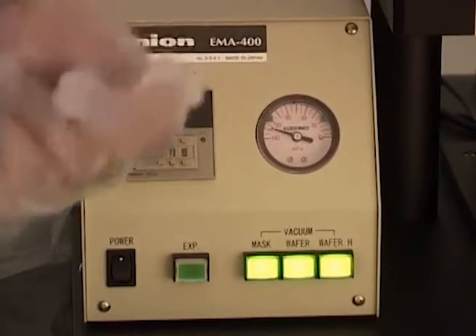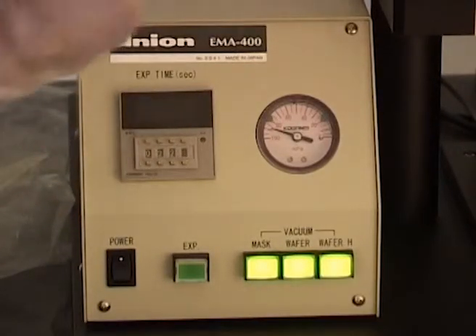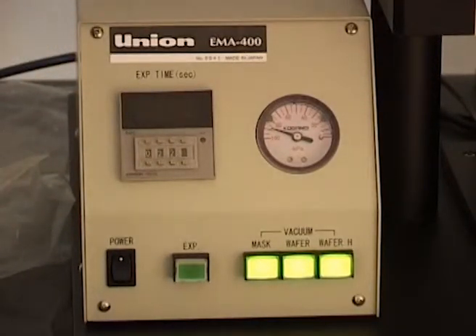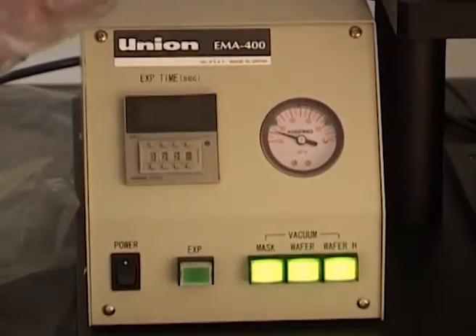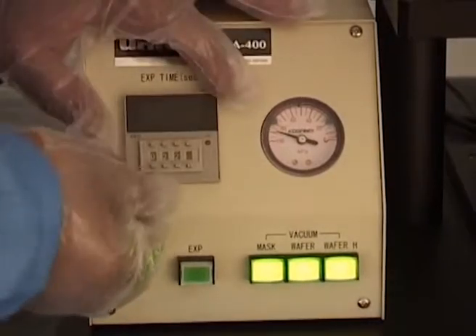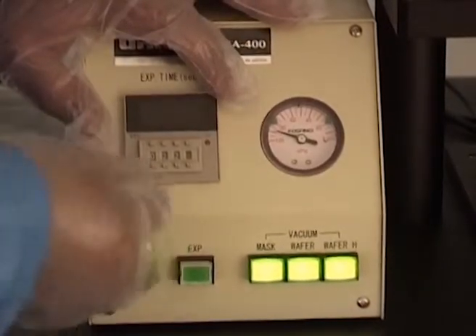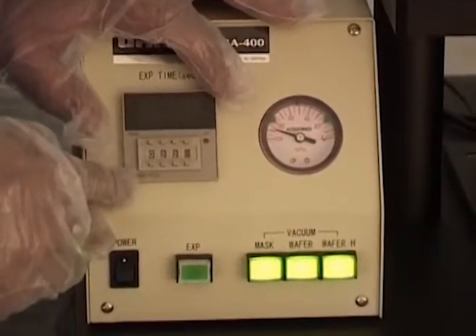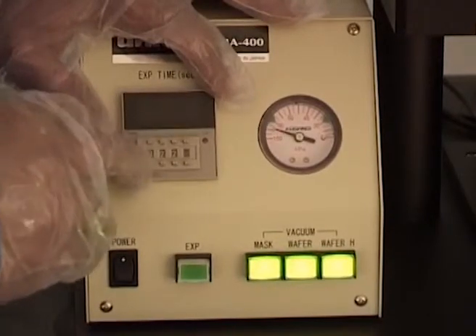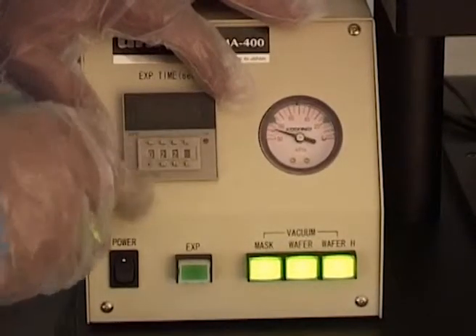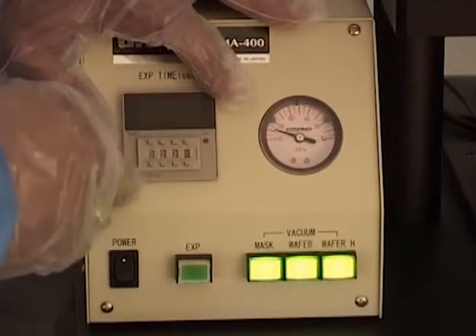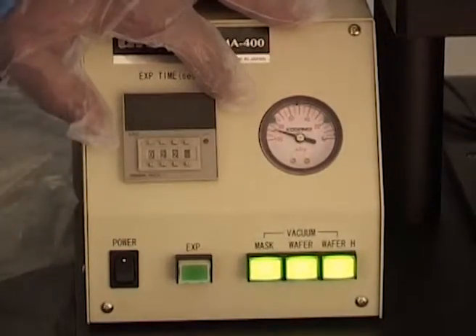Because our thicknesses of the resist are about 20 to 25 microns, we can get the correct exposure at the dosage rate that this particular lamp offers in a time of about 20 to 22 seconds. We use this timer setting for achieving that. So you have these different values here in seconds, and you can see right now the setting is about 22 seconds here, which means that the exposure would be for 22 seconds.